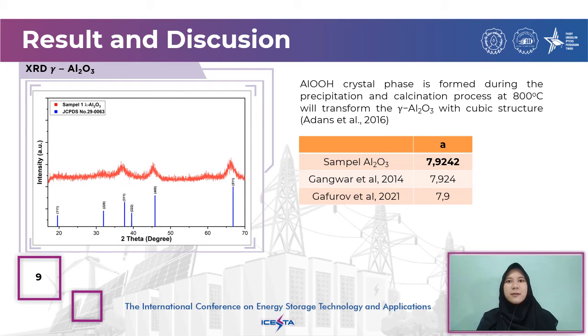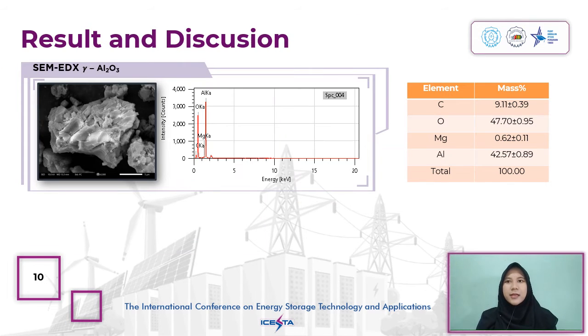Based on JCPDS standard number 29-0063 data, the alumina sample has been successfully extracted from the beverage can because it has a diffraction pattern that forms the cubic structure of aluminum oxide. The lattice parameter of the aluminum oxide sample is 7.92 Angstrom, which is suitable with the result reported by Gafurov et al. Here's the particle morphology of aluminum oxide from the beverage can extraction, distributed from 1.2 to 4.2 micron in diameter. The EDX curve displays the presence of metals such as 42.57% aluminum, 47.7% oxygen, and also some magnesium and carbon.